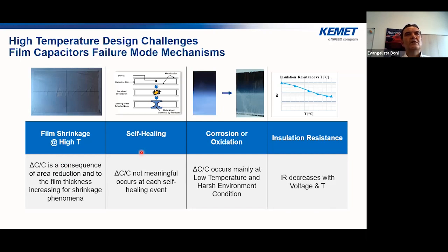Self-healing is a well-known property of the film capacitor that, together with the flexibility of the film, is the true secret of the high reliability of the film capacitor. We can say that each self-healing event is not meaningful for the capacitance drop, but of course, with increasing high temperature, the number of events can increase, and this should be taken into account during the design.